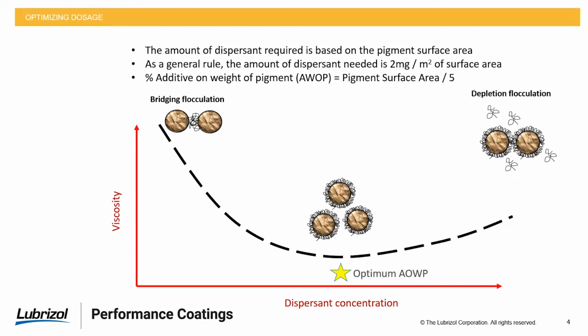Now, in practice, we recommend that you do a dispersant demand curve where you make a series of dispersions and you measure viscosity against the dispersant concentration, or the particle size versus the dispersant concentration. And we'll often find that the optimal properties correspond with the optimal additive on weight of pigment. That might be a minimum of viscosity, a maximum of color strength, a minimum of particle size. And you can see from this graph, where we're plotting viscosity versus the dispersant concentration, that we follow a declining curve of viscosity until we approach the optimum additive amount. And then once we pass the optimal additive amount, our viscosity will ultimately begin to increase again. And so there is a sweet spot around our viscosity or our particle size minimum.